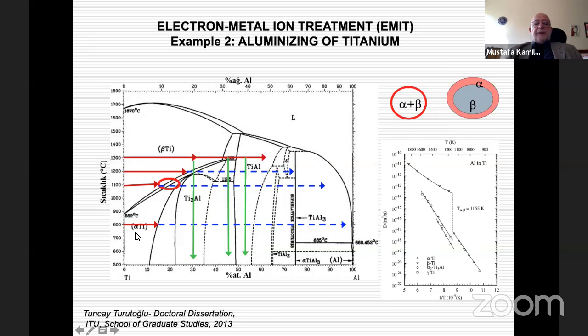First, in alpha titanium, the diffusion of aluminum in the solid solution region is very high, and then it becomes very low. In beta titanium, again, we have a very high diffusion rate in the solid solution region, and then it may change depending on the process. So let's start with the alpha region. When you conduct your tests at 800 degrees, you start to alloy titanium with aluminum up to a content of approximately 10%. If you stay in this range, you just have a titanium aluminum solid solution.